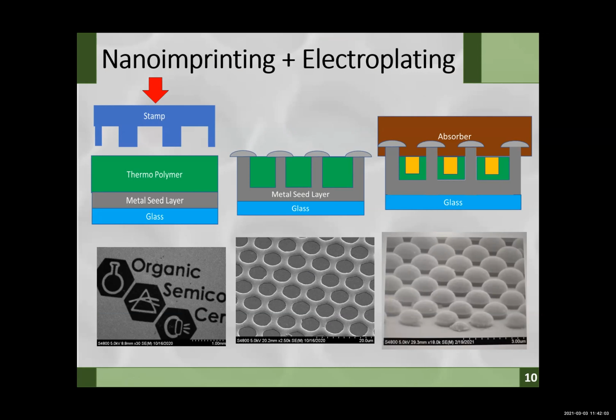Yes, we do use copper. We can also use other metals such as nickel and gold. Diffusion is an issue. I've massively simplified these structures. So usually, after we have deposited the copper or the nickel, we will coat them with an oxide layer as well, which prevents diffusion and also provides charge selectivity. So that's one of the avenues I'm researching.